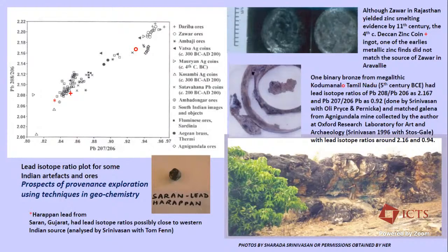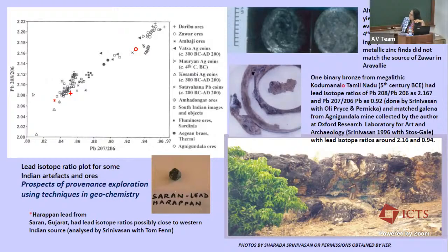Why this is also interesting is because quite often it's suggested that because there was so much more copper ore in the north, in the Aravallis and so on, those might well have been the sources for some of the bronzes we've been talking about. But this suggests that there was already exploitation of the South Indian mine by this period. This is the Agnigundala region. And Zawar, you can see here, has lead isotope ratios falling somewhere up there.